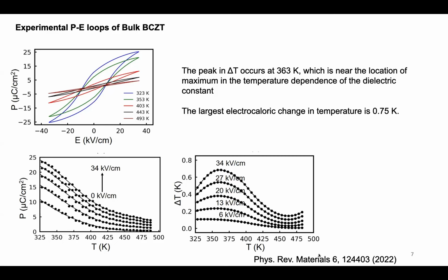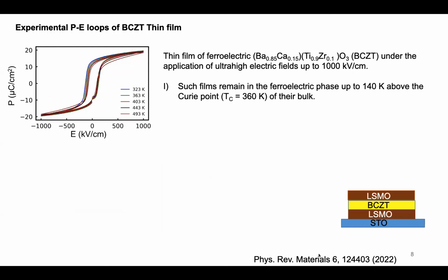So that's what I wanted to show from their observation and how we tackled that from the theoretical perspective. So here is the result on the thin films. The films were grown on the STO substrate with the LSMO as electrodes, and the films were of thickness, if I remember, 120 nanometer, and this is the P loops from the experimental data. And the field, the maximum is around 1,000 kV per centimeter.